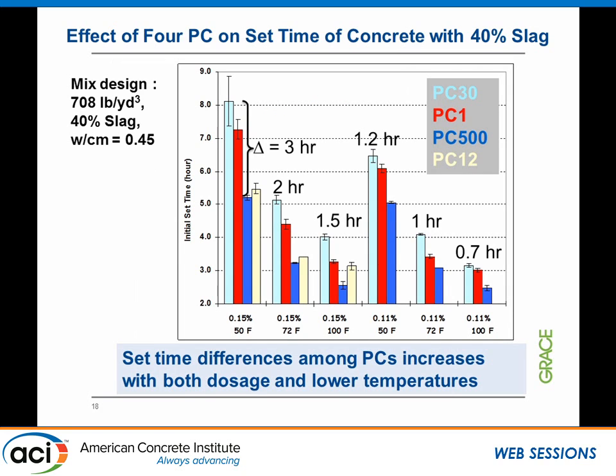So in here, I show you an example where we are looking at a mix design that's using 40% slag. Okay, we are looking at a 0.15% dosage level versus a 0.11% dosage level of 4 different polycarboxylates, where we made the concrete at 72F and then cured them at 50, 70, and 100F.